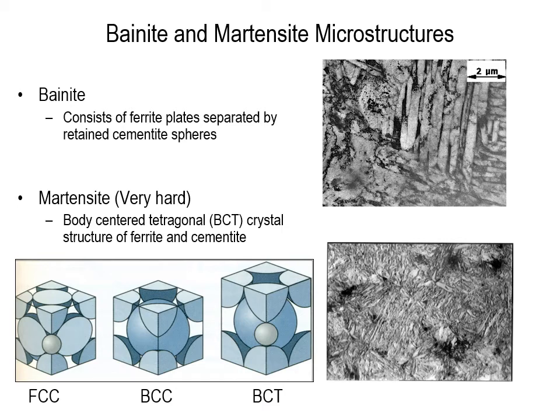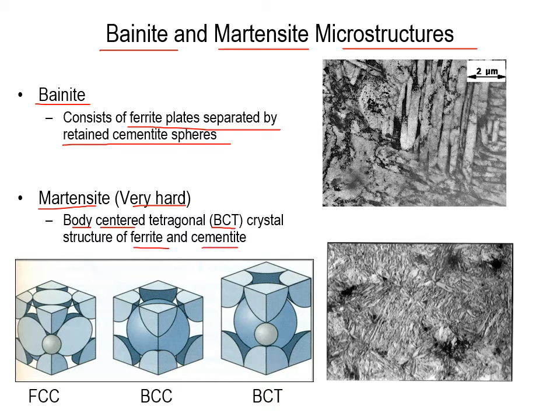Now we're going to discuss our bainite and martensite microstructures. Bainite consists of ferrite plates separated by retained cementite spheres. And we have martensite here, which is very hard, and this is going to induce a BCT, a body-centered tetragonal crystal structure of ferrite and cementite. If we look down here, here's our FCC, our BCC, and now our BCT structures, and we can see the difference between all of these.